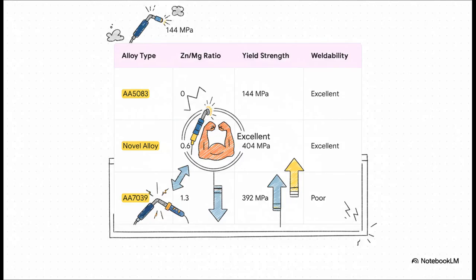And the data? The data proves it works, big time. A standard weldable alloy, that 5000 series, has a strength of about 144 megapascals. That's just a unit of pressure. The unweldable 7000 series is way stronger at 392. But now, look at the new alloy in the middle. It welds perfectly, and it has a strength of 404 megapascals, even stronger than the original. They didn't just find a compromise, they actually created something better.